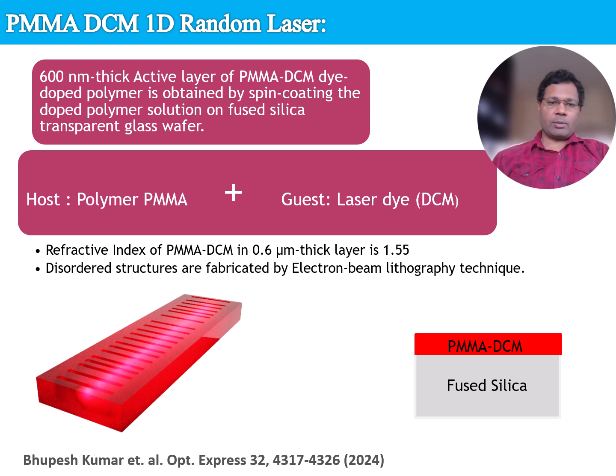We have designed and fabricated our own custom disorder structure embedded with gain medium to study random lasing phenomena. The passive host polymer was PMMA, polymethyl methacrylate, with a molecular weight of 49500, doped with a 5% weight of laser DCM dye. A uniform layer of approximately 600 nanometer thickness was deposited by spin coating the doped solution at 1000 rpm for 60 seconds, followed by a post baking at 120 degrees Celsius for 2 hours to evaporate solvent and ensure solid and stable film.